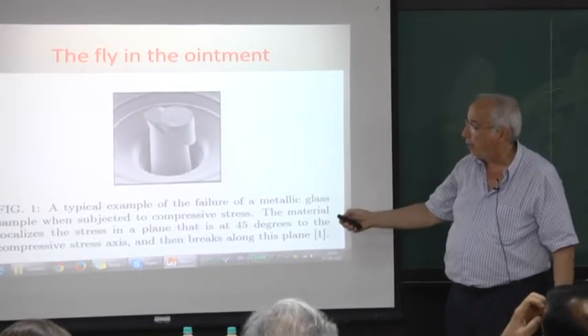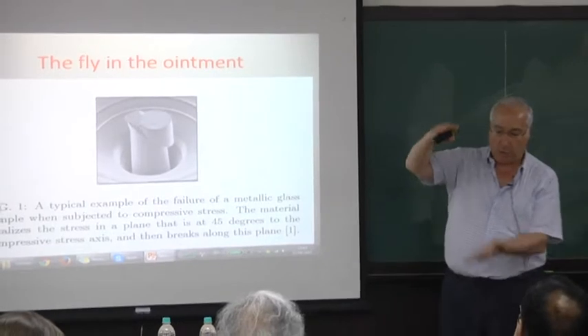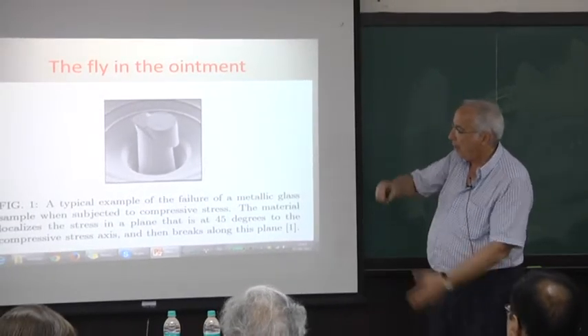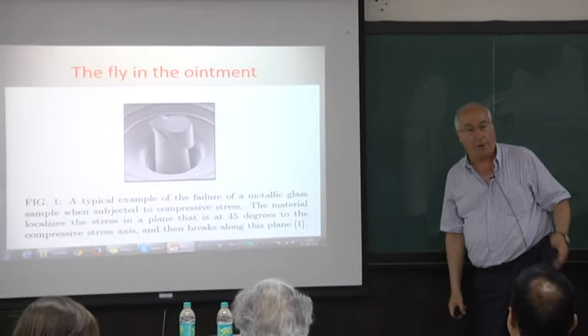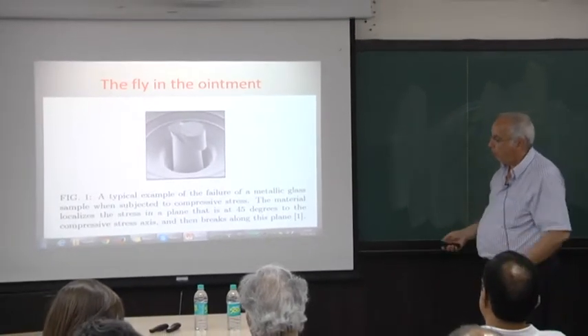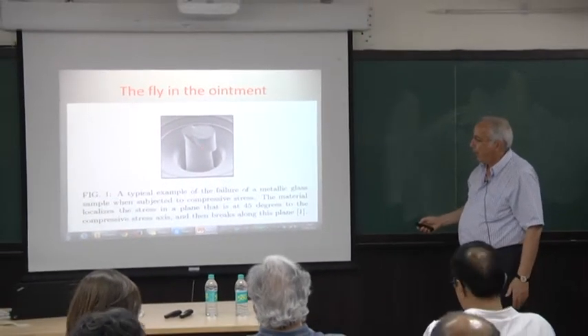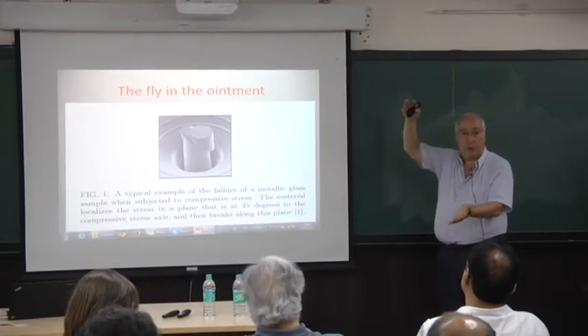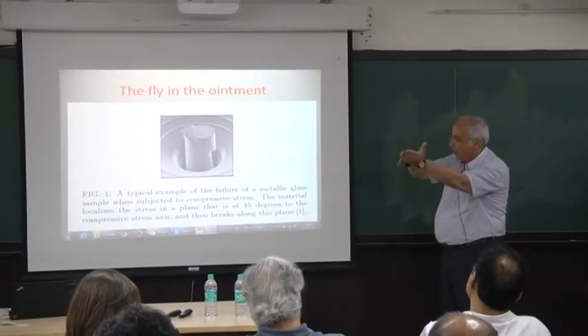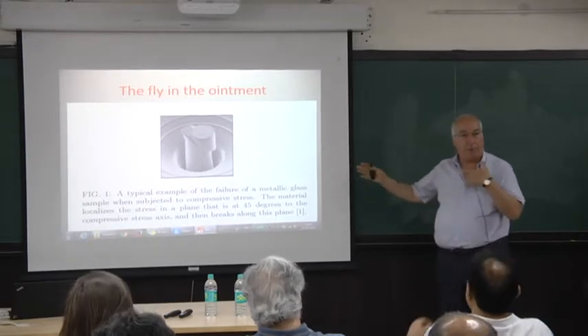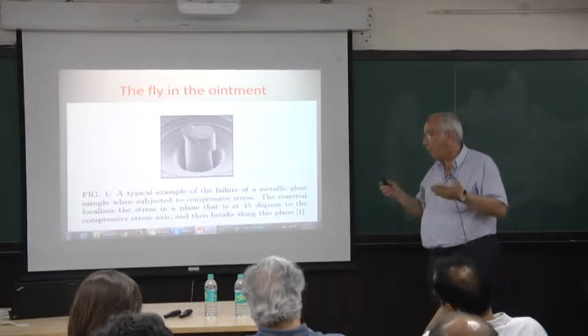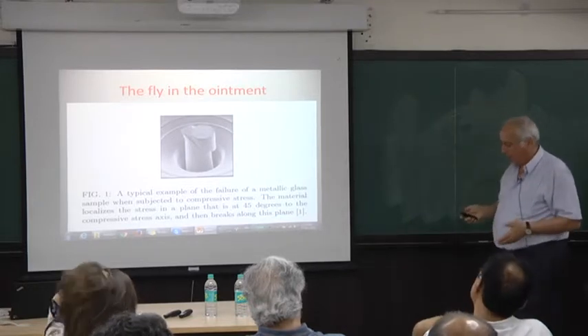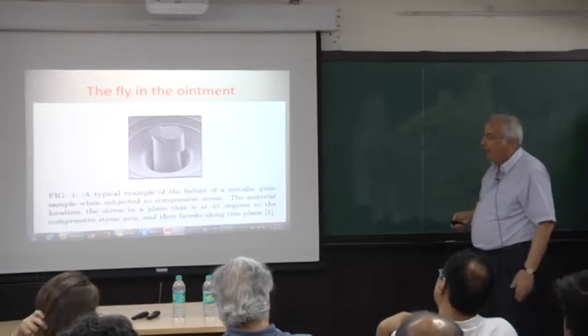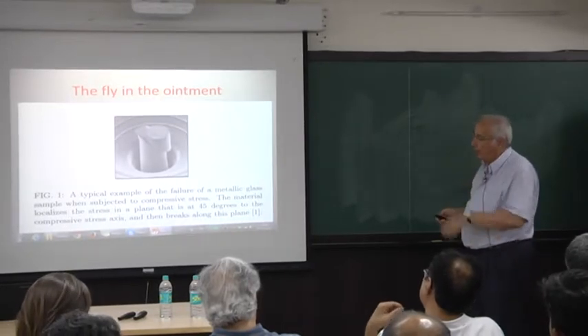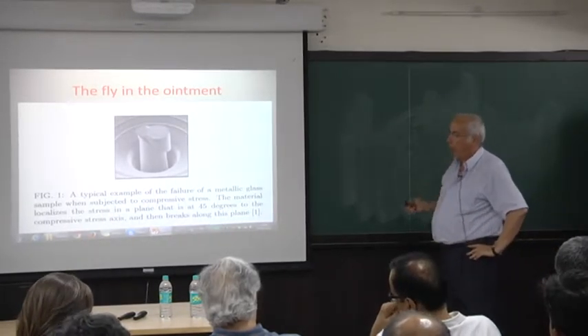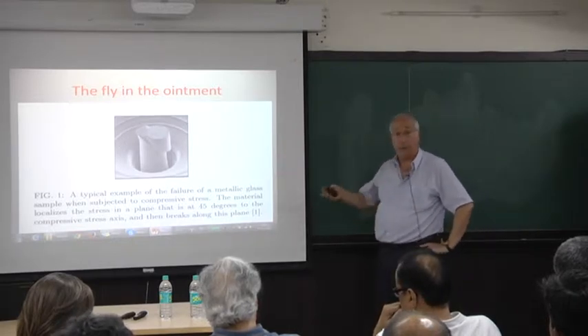And then this thin layer is roughly at 45 degrees with the external strain. I show you this: 45 is not always 45. It's to first order approximation about 45 degrees. And all the stress, all the strain is concentrated in the thin layer, and then the system there breaks. This is the phenomenon that I want to actually understand, and of course, understanding with the hope in general that we can delay it or avoid it in order to make these materials more readily available for technological applications, which are coming anyway.